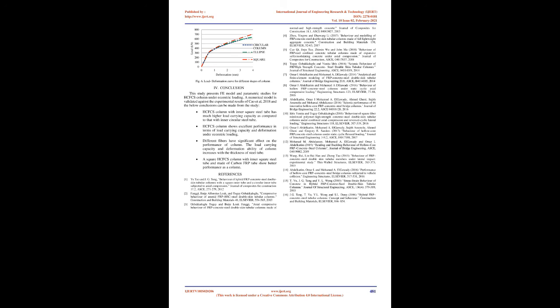Conclusion. This study presents FE model and parametric studies for HCFCS column under eccentric loading. A numerical model is validated against the experimental results of Cao et al. 2018 and the below conclusions can be made from the study. HCFCS column with inner square steel tube has much higher load carrying capacity as compared to that with inner circular steel tube. HCFCS column shows excellent performance in terms of load carrying capacity and deformation under eccentric loading.